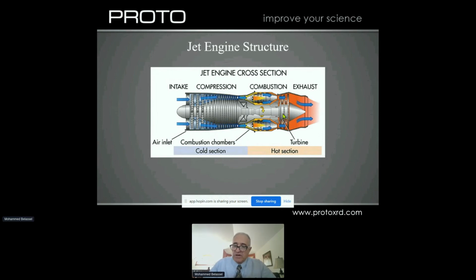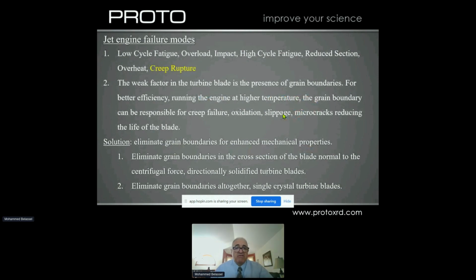That means they have to avoid catastrophic failures because of these blades that were made of polycrystalline materials in the past. They have to go to single crystal materials. One of the problems they have with the presence of the grain boundaries in materials is creep rupture, and also associated with that oxidation, slippage, micro cracks, thus reducing the life of the blades. When they started back then, they tried to eliminate the grain boundary that is perpendicular to the grain longitudinal direction, in the radial direction, where the centrifugal force is applied.